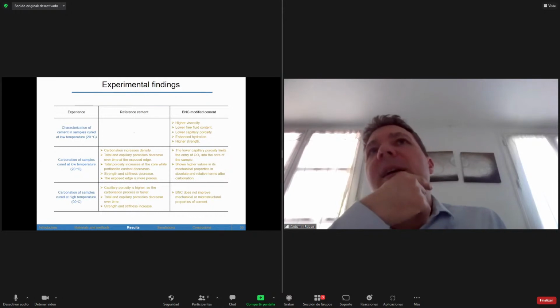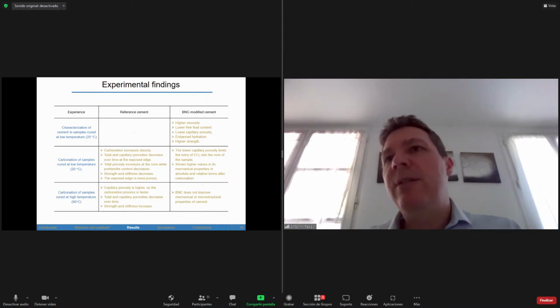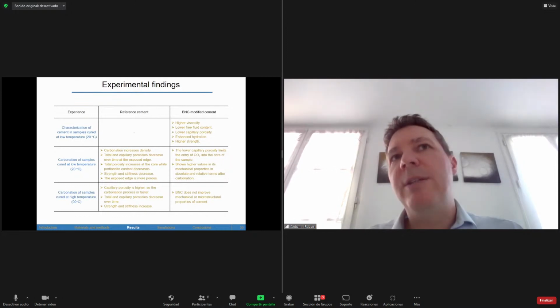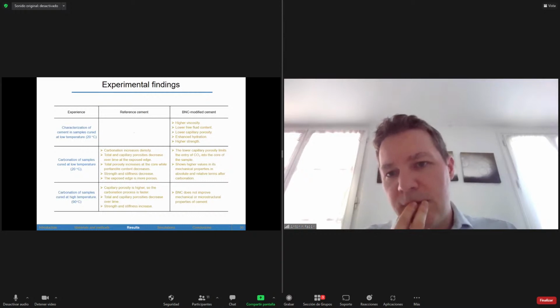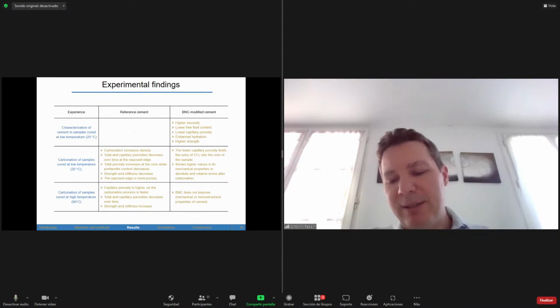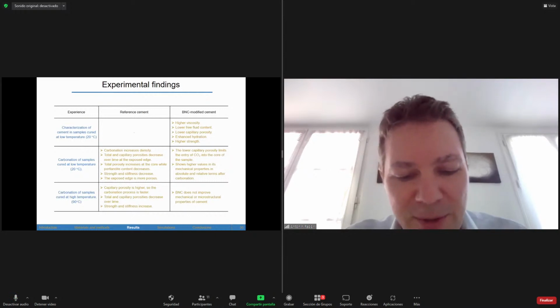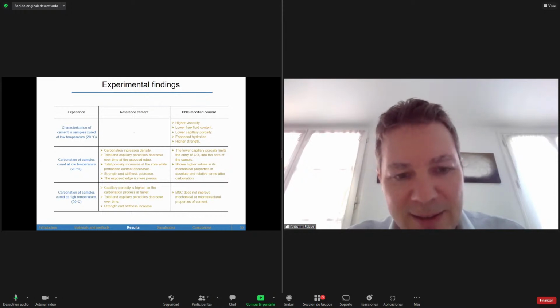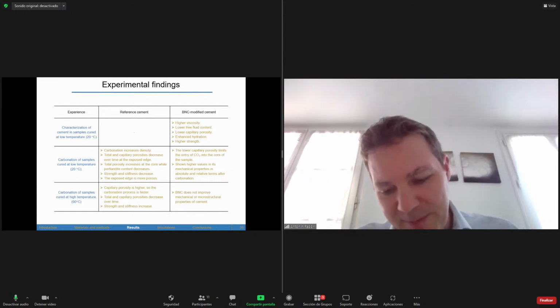Okay, so why have you not tested a situation where you got the sample at high temperature but with no drying? Because maybe this drying and wetting process can damage the sample, no? We wanted both carbonation methods to be comparable, so that's why we decided to saturate them both before carbonation. But that was the main reason.